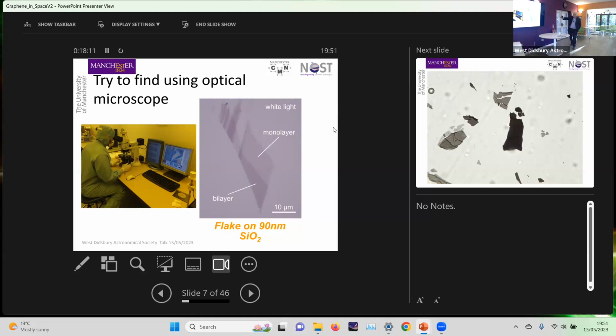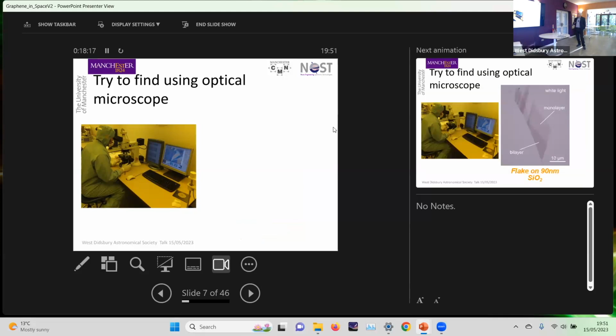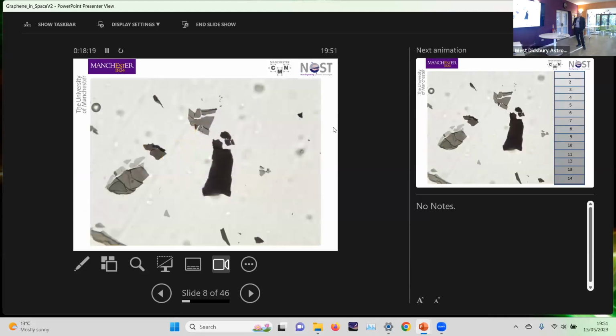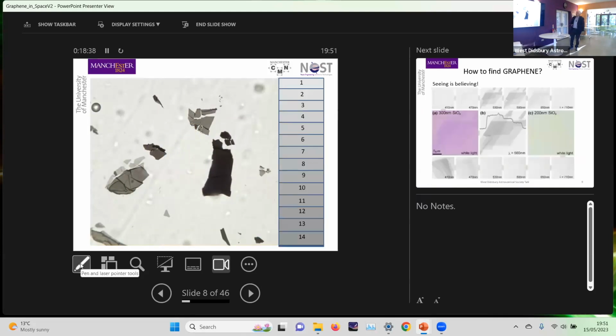You can see there's a bilayer there as well. Note the contrast, very high contrast. I'll come back to that in a minute. So if we looked at that tape you're looking at now under a microscope, this is what we would see. Okay, and you can see that some areas are just chunks of graphite, and other areas are much, much thinner. And you can see some very thin, transparent areas.